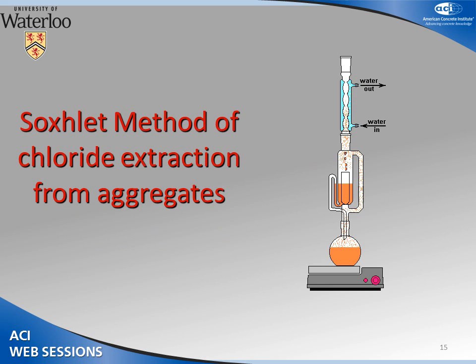Well, I'm sure many of you don't know what the Soxhlet method is, so I'll quickly explain it to you. The specimen is put into a porous container here. And the solution, if you want to have water extraction, that would be water. If you want to have acid extraction, that would be acid. It's put into here. This is heated up. It evaporates up into this condenser area here and condenses out and drips into this area where the specimen is. When this becomes full, it will overflow and go back into the solution and so concentrate. And over a 24-hour period, you get out all the chloride that's ever likely to come out. This was accepted by the ACI 222 committee and is now one of the standard practices that's recommended for extracting chlorides.